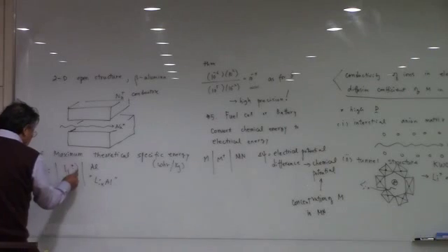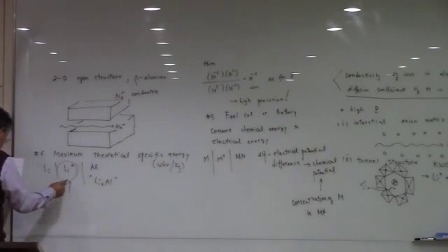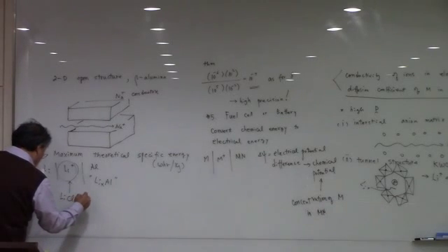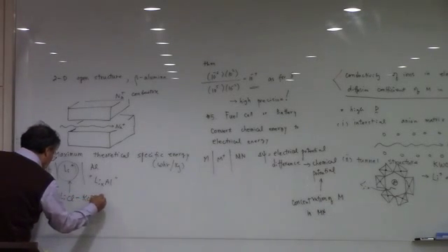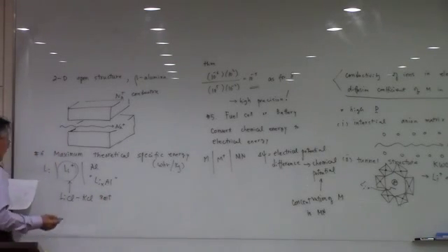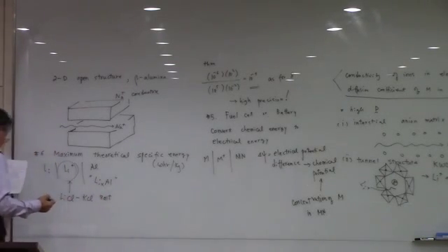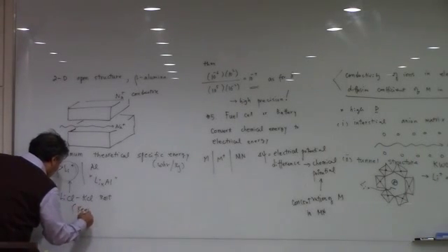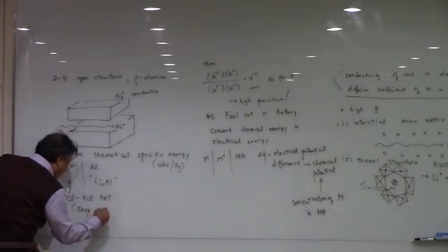And for this lithium conductor, we usually use LiCl and KCl salt, which is a high lithium ionic conductor at the temperature 400 degrees centigrade.